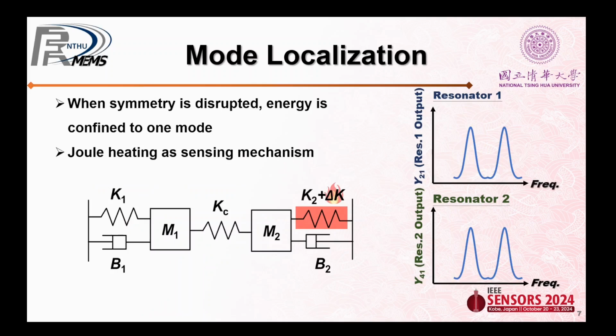Now let's introduce the sensing signal, the DC current. There's a heating path on the support transducer of the resonator. The current generates heat through Joule heating. Because the Young's modulus of the material is temperature dependent, the stiffness of the heated resonator changes. So this introduces asymmetry, leading to the change of the output amplitude ratio.